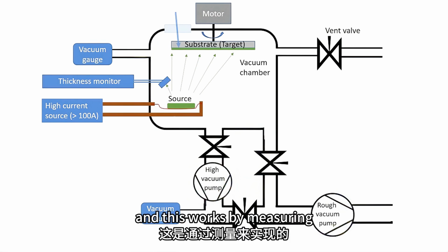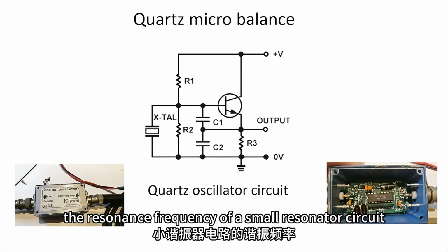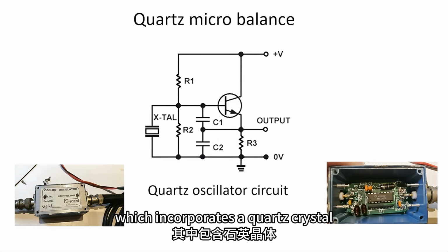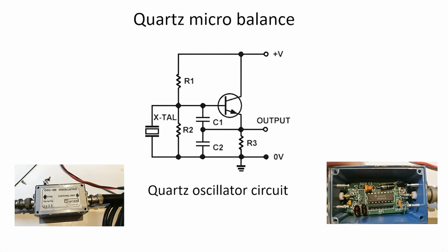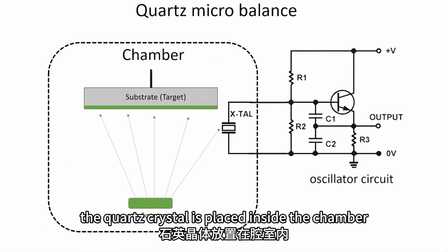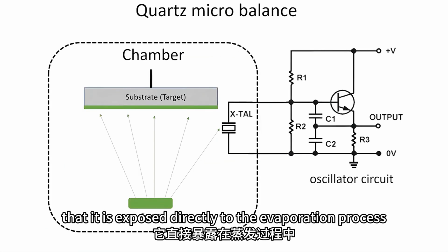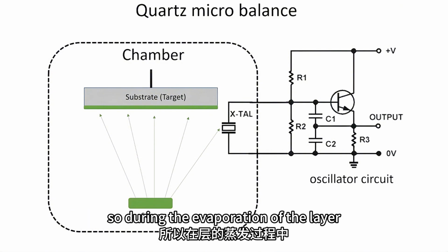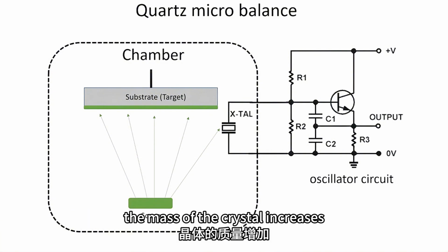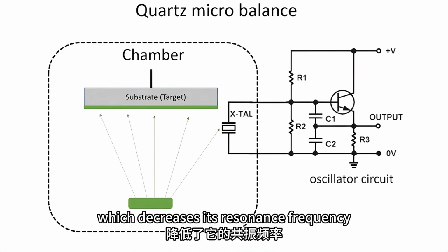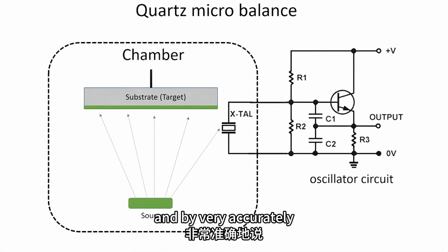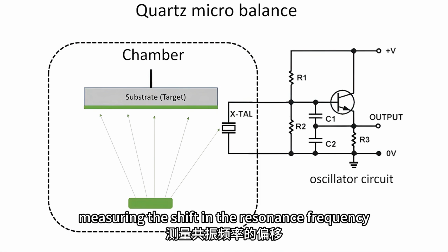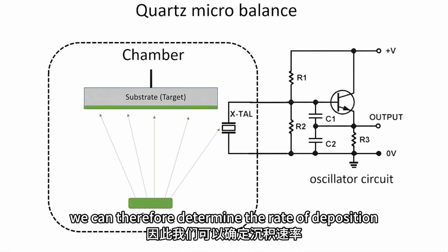This works by measuring the resonance frequency of a small resonator circuit, which incorporates a quartz crystal. Now, the quartz crystal is placed inside the chamber in such a way that it is exposed directly to the evaporation process. So during the evaporation of the layer, the mass of the crystal increases, which decreases its resonance frequency. And by very accurately measuring the shift in the resonance frequency, we can therefore determine the rate of deposition.